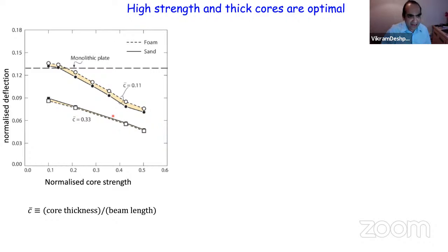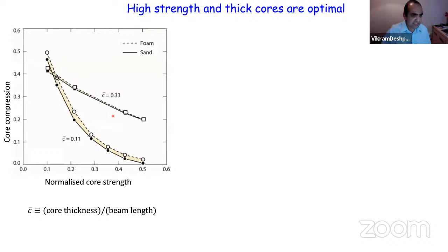So the question is, why is it the case? Why are the simulations doing this? And the answer is rather simple: as you increase the core thickness or the core strength, you decrease the core compression. And when you decrease the core compression, you retain the bending stiffness or bending strength of the sandwich beam. This is traditional sandwich theory, really, telling you that if you separate the face sheets by a large amount, you will increase the bending strength. And that is a very simple reason why you are basically getting this effect of a thick core and a